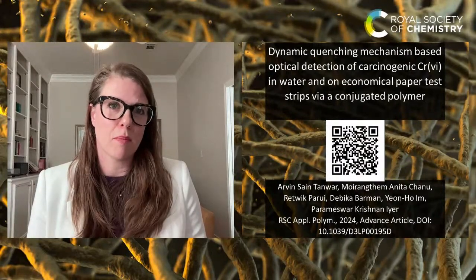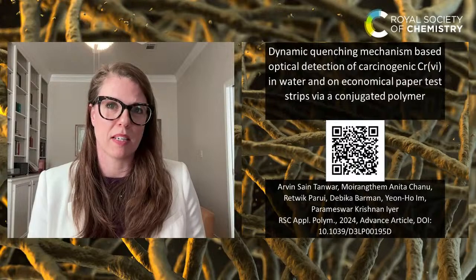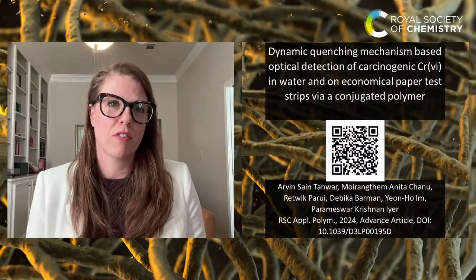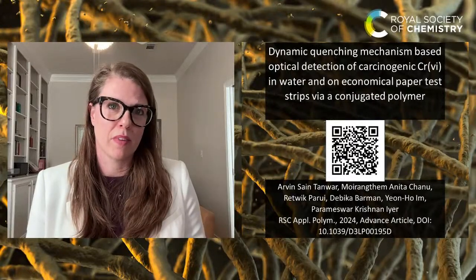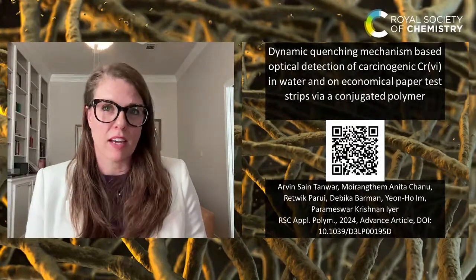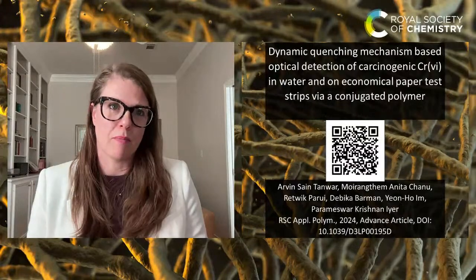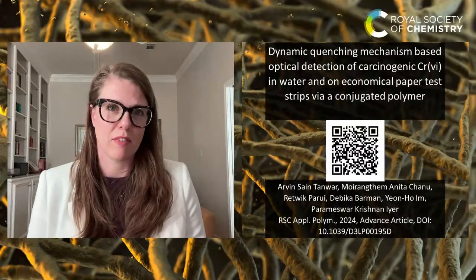They demonstrated that the polymer is highly sensitive to chromium-6 and highly selective by comparing the performance to interfering metal ions and different anions. The system has a low limit of detection of 6.8 parts per billion, which is lower than the World Health Organization safety limit.